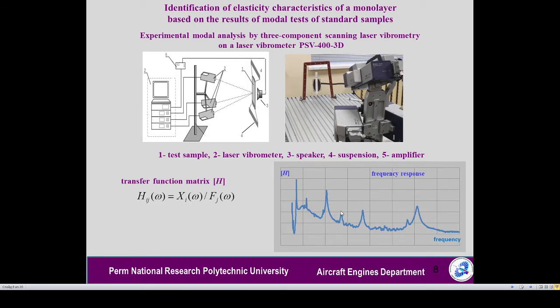The method of scanning laser vibrometry was used. The sample was attached to a rigid frame on thin elastic threads. Sample's vibrations were excited by an acoustic shaker and recorded using a scanning laser vibrometer PSV-400-3D. Thus, the tests were performed without contact of equipment with the sample. This made it possible to determine with high accuracy the first 8 natural frequencies in the range up to 2000 Hz.